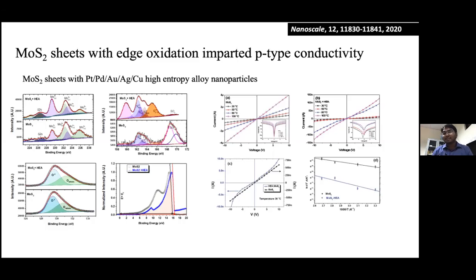MoS2, if you look at the band structure, whatever reports have said, it should have an N-type conductivity. That means it should have some sulfur vacancies. Sulfur vacancies will give some kind of donor impurities, and the donor impurities will give you a carrier concentration of electrons. Now, what we instead found is that from the response, it was showing p-type conductivity, which was contradictory to what we expected. And on the other hand, the MoS2 which did have these high entropy particles and the one which did not have these particles were showing very different electric behavior.